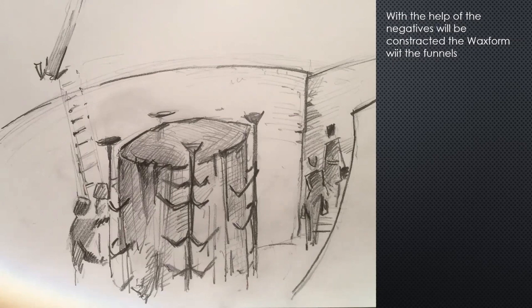The direct sunlight was dangerous not only for handling the wax. The wet clay developed cracks if it dried too fast, especially the layers of finely graded clay. To prevent that danger, the casters used three-legged levers above the pits. If one leg was facing directly south, sails spanned there could block the sun coming from the southeast, or during sunset, the southwest. At the same time, some cool air was allowed in from the open north side.